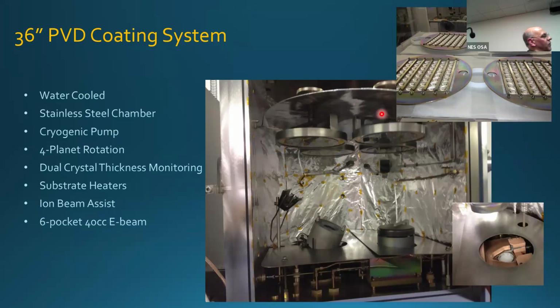And that's because with physical vapor deposition, you don't have a uniform plume of material that's condensing. It's distributed radially. So it may be a very high concentration of film coming from the E-beam gun, but as you get further away, you get less concentration. So the thickness would be thinner. In order to get the uniformity, we have to rotate the substrates in and out of the film plume, if you will, in order to even out the thickness distribution.